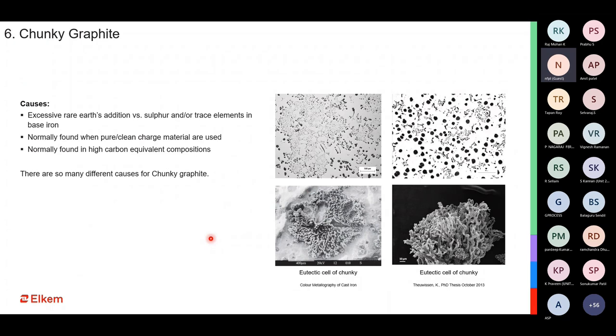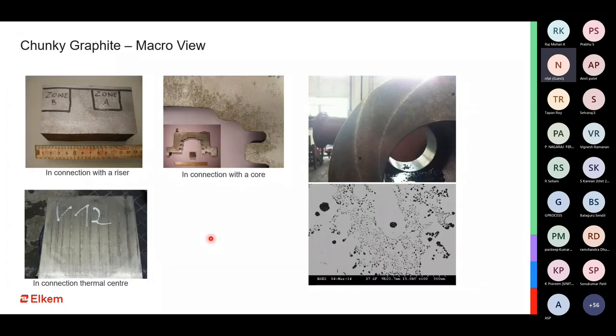Why do you get this? You get this when you have excess rare earth, again the same reason. In the case of exploded graphite, it can also happen when you have high carbon equivalent, but in the case of chunky graphite, you get this when you have high carbon equivalent along with a high percentage of rare earth in the system. In fact, for chunky graphite, you don't even have to cut and check the micro. Even on the surface, you can see some amount of blackish, darkish, graphite flotation-like features. Even chunky graphite is visible just from the cut section.